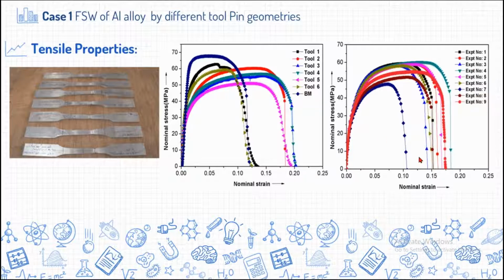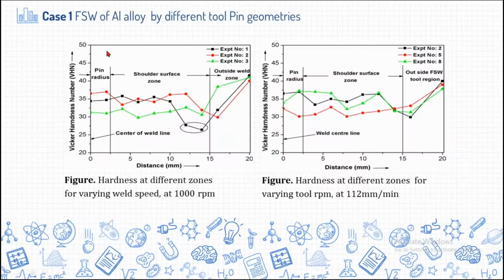So for all the experiments, these are the values we plotted for stress versus strain, and these are the hardness plots for different tool pin geometries. If you see at the pin center of the welding, hardness values are around here for Vickers hardness testing, and outside the welding zone, this is the base material zone. Between the center of the welding zone and the area outside it, in the base material area, hardness values do not vary much, almost close to the base material.